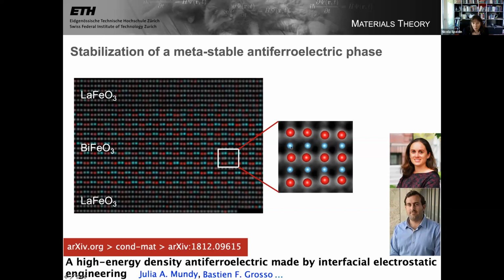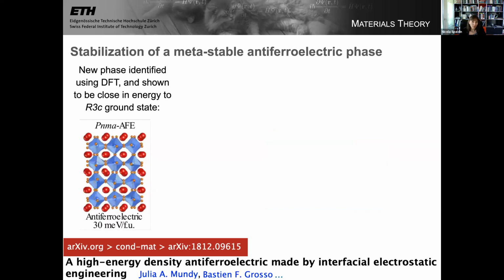The blue circles are the ions. Then we have a row of bismuths not going anywhere, and then a row of bismuths where two go down directly below the two that went up before, and then two go up where the two went down before. And so Giulia came to us and said, well, what on earth's going on here? They had these microscopy images, but this kind of pattern of bismuth displacements did not correspond to any known phase of bismuth ferrite.